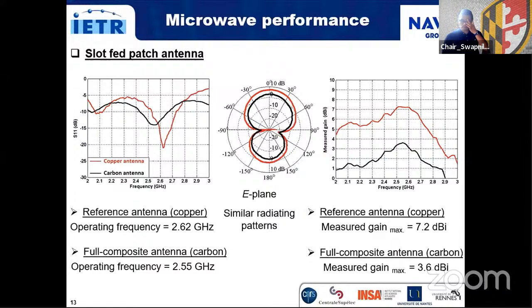Let's move to the microwave performance of such antennas for Wi-Fi application. Both antennas, the reference one and the full composite antenna, exhibit an operating frequency close to the Wi-Fi band, with similar radiating patterns here. As expected, the full composite antenna exhibits lower gain value compared with that of the reference one, mainly due to ohmic loss in the carbon feeding line. Carbon is not a metal. Nevertheless, with a measured gain equal to 3.6 dBi, the full composite antenna is fully operable for Wi-Fi application.